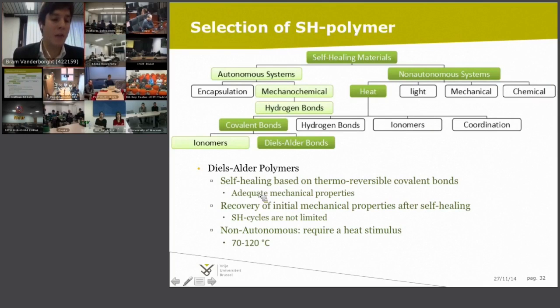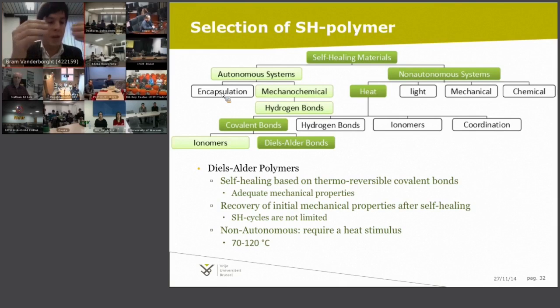One of the other advantages of the Diels-Alder bonds is that the number of self-healing cycles is not limited. When you have, for example, little capsules of self-healing material and a crack appears, the capsule opens and the material can self-heal. But that also means you can only use those capsules once, while with the Diels-Alder bonds, we can have a cut, self-heal, have another cut in exactly the same place, heal it, and so on. Moreover, the required heat stimulus is quite limited. It's between 70 and 120 degrees Celsius, which is okay.